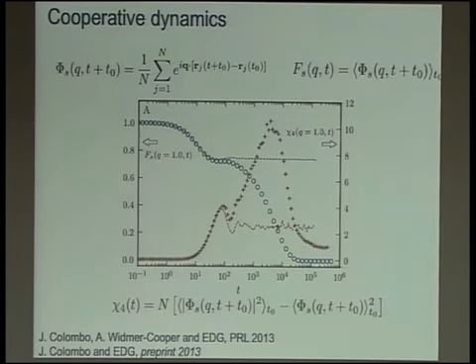And this fluctuation actually measures the enhancement of correlation in the particle displacement due to the fact that the dynamics is cooperative, and this is what produces this type of complex decay of the relaxation function. The interesting thing here is that if we compare this function with the one that we measure in the frozen network, which is this dashed line here, one can see that the signal of this cooperativity, as it is captured by this function, is basically negligible in the constrained network, and instead becomes significant in the restructuring network. So this tells us that the restructuring of the network is actually happening in a cooperative way, and this is what is probably interesting also if one thinks of the problem I was mentioning before.